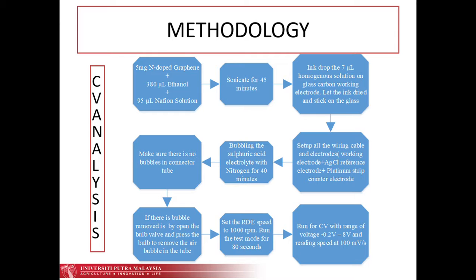Then we set up all the wiring, cables and electrodes, which are the working electrode, silver chloride reference electrode, and also platinum counter electrode. After we set up all the wiring and the electrodes, we bubble the sulfuric acid electrolyte with nitrogen for 40 minutes. After the bubbling, we have to make sure there is no bubble in the connector tube because it will affect the result. If there is a bubble, remove it by opening the bulb valve and pressing the bulb to remove the air bubble in the tube. Then we set the rotating disk electrode speed to 1000 rotations per minute and run the test mode for 80 seconds.